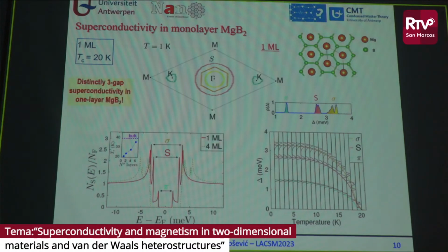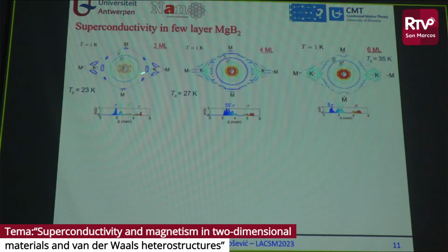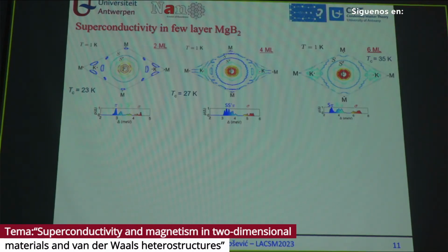Okay. If we add a layer, if we go to two monolayers, everything changes, and these surface gaps, this is now an additional surface gap due to boron, they all interconnect into one big anisotropic gap. Although you can separate the origins of superconductivity at different energies, these gaps are interconnected. The same at four monolayers, but then at six monolayers, again, you start to get a sense of three-gap superconductivity. So superconductivity changes strongly.